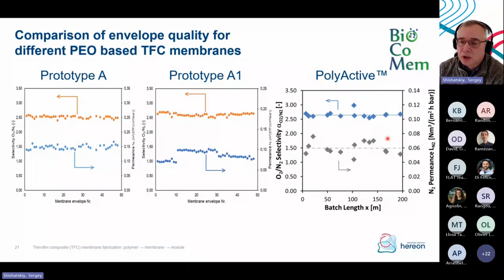And as a comparison, you have properties of a PolyActive membrane, our standard membrane, which we try to put into practical application. What you can see here, permeance for nitrogen is 60 liters of nitrogen per square meter. For prototype A, we have 150 liters, so it's 2.5 times faster than PolyActive. And for prototype A1, which was twice thicker, we have roughly 75 liters per square meter hour bar, which corresponds to the thickness observed in the AFM image.